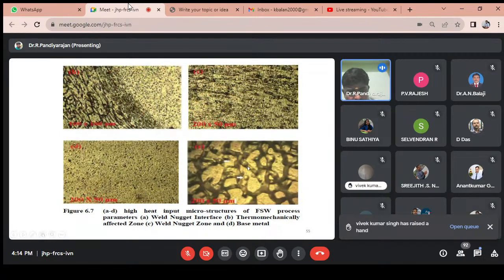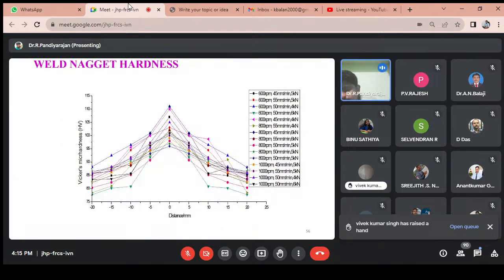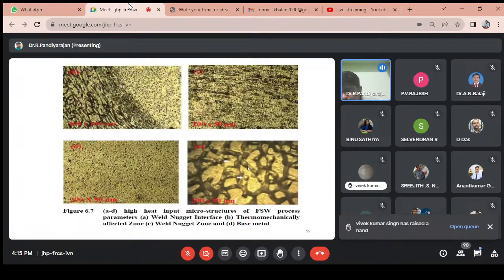thermomechanically affected zones, and the third image shows the weld nugget zone. Finally, the fourth image shows the base metal of the composite material. This is the sample image of microstructure analysis in welded joints with optimized process parameters.